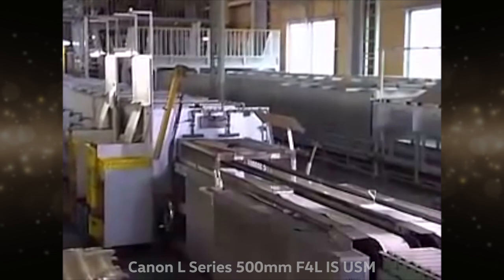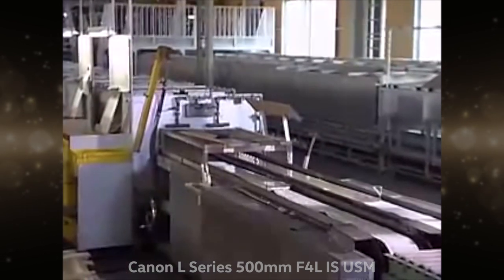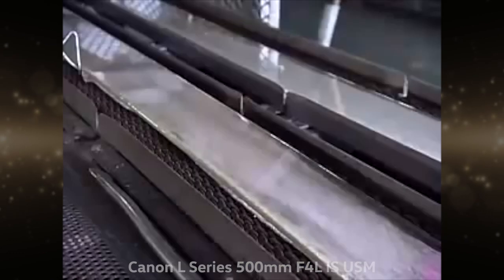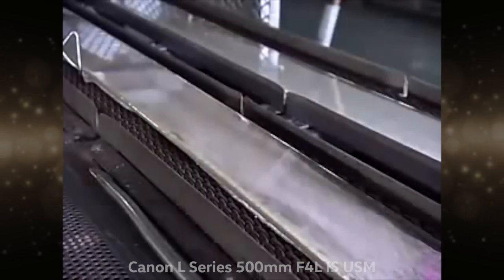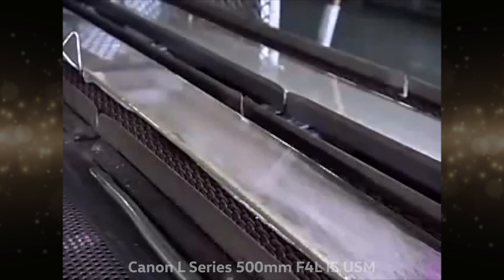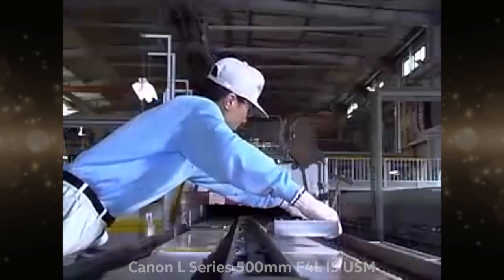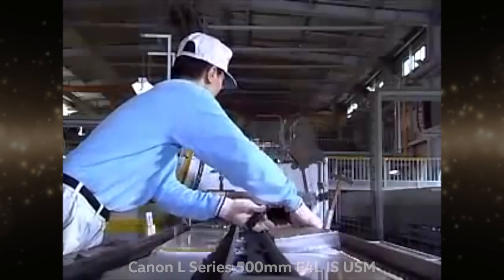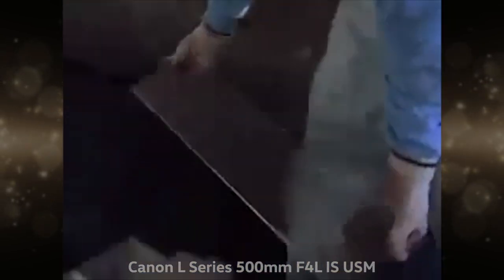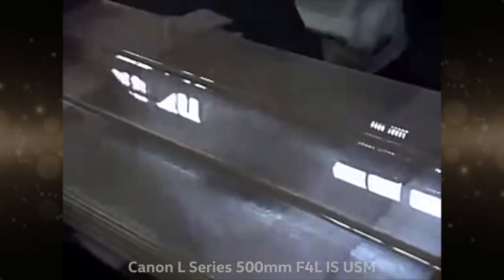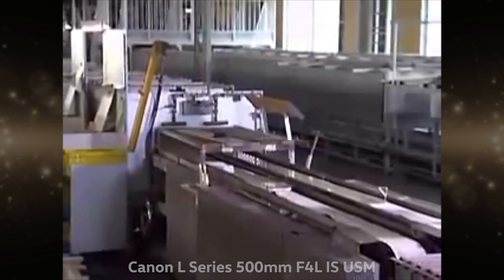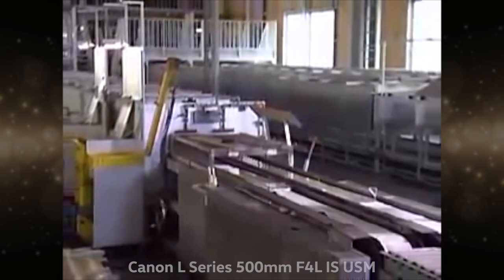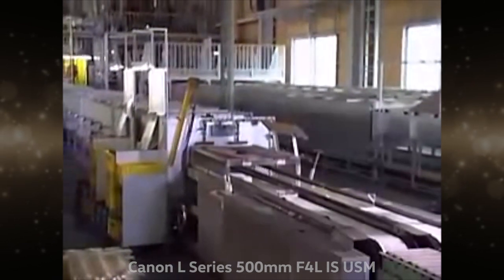Poured into the shaping part, the liquid glass is shaped into a sheet. This sheet is gradually cooled to room temperature while traveling on a conveyor belt through a temperature gradient type continuous slow cooling furnace. The sheet glass produced by this process is used as the material for individual lenses. In high quality optical glass production, the fusing and cooling processes are the most important.